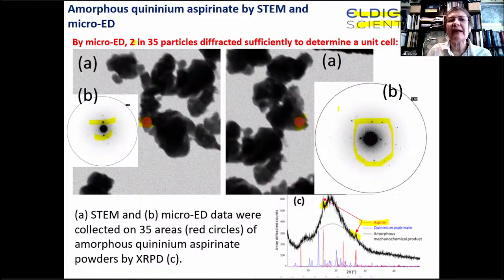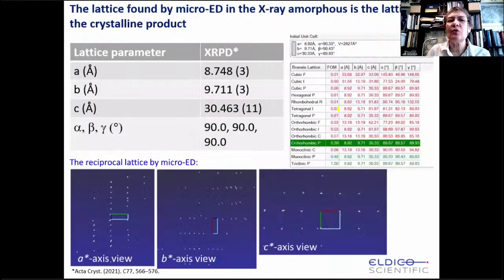So these two diffracting particles were sufficient to actually determine a unit cell. And the unit cell we can see here, determined by microcrystal electron diffraction, was the unit cell of the crystalline product that is obtained with liquid additives. So the numbers are very similar. And we can see here the reciprocal lattice by micro-ED. So then it appears that this amorphous powder diffraction actually contains a certain fraction of crystalline or poorly crystalline particles of the product.